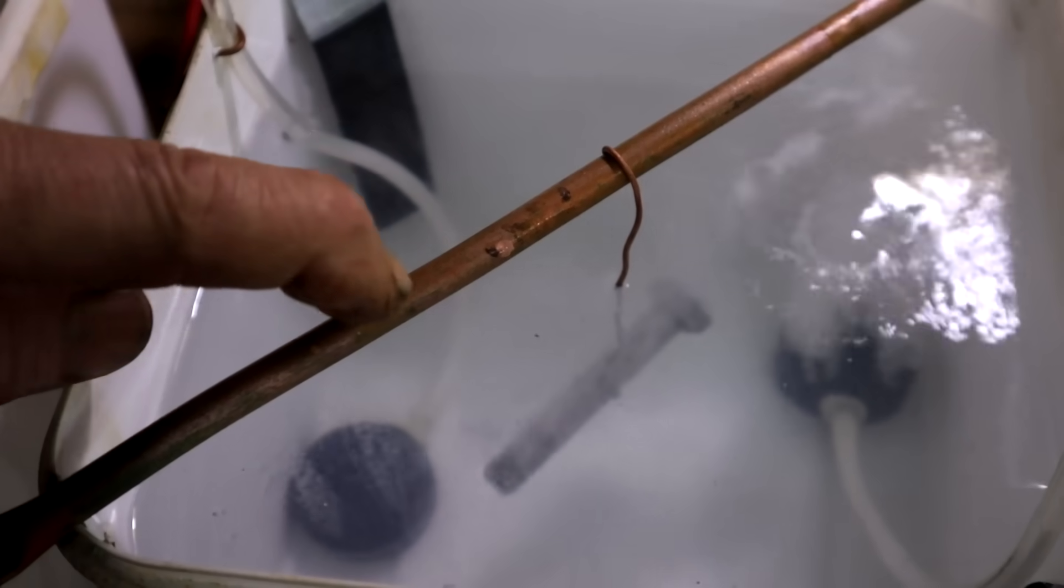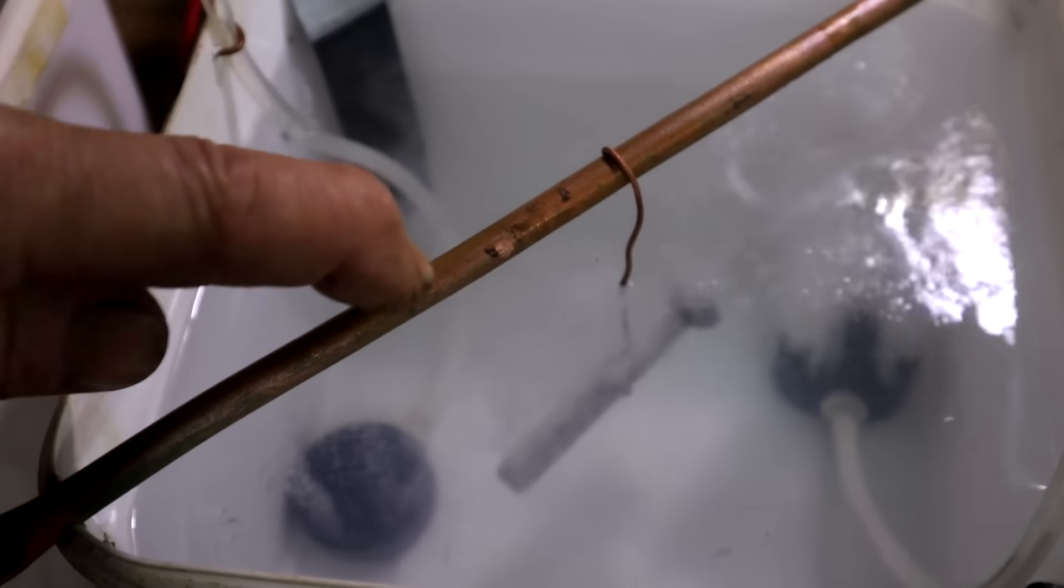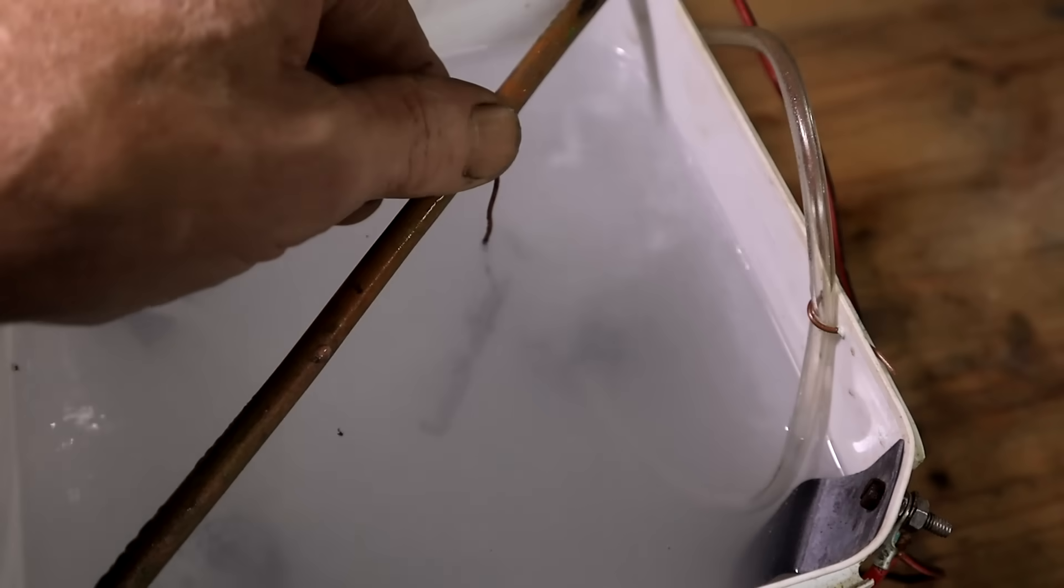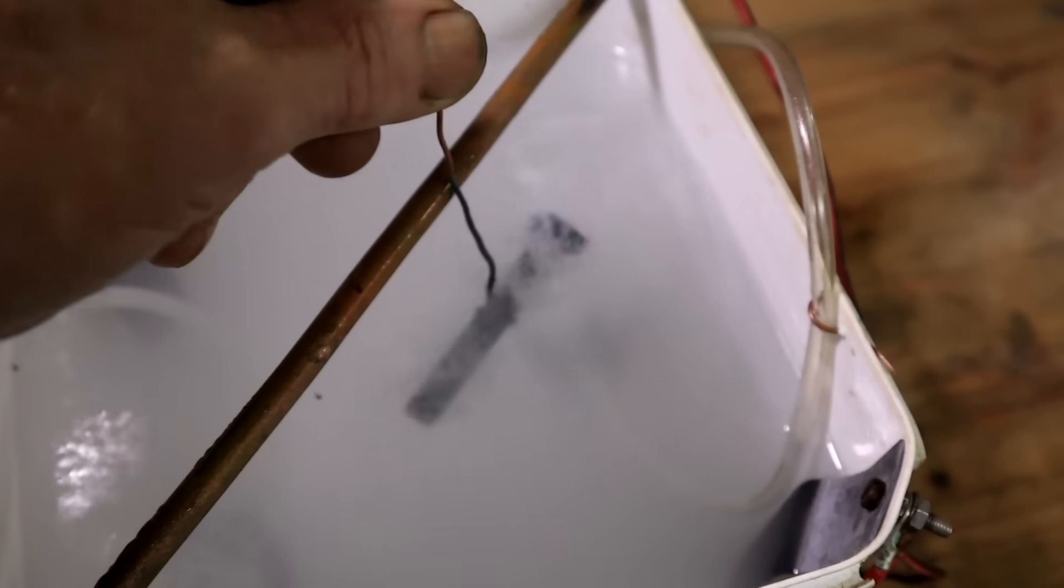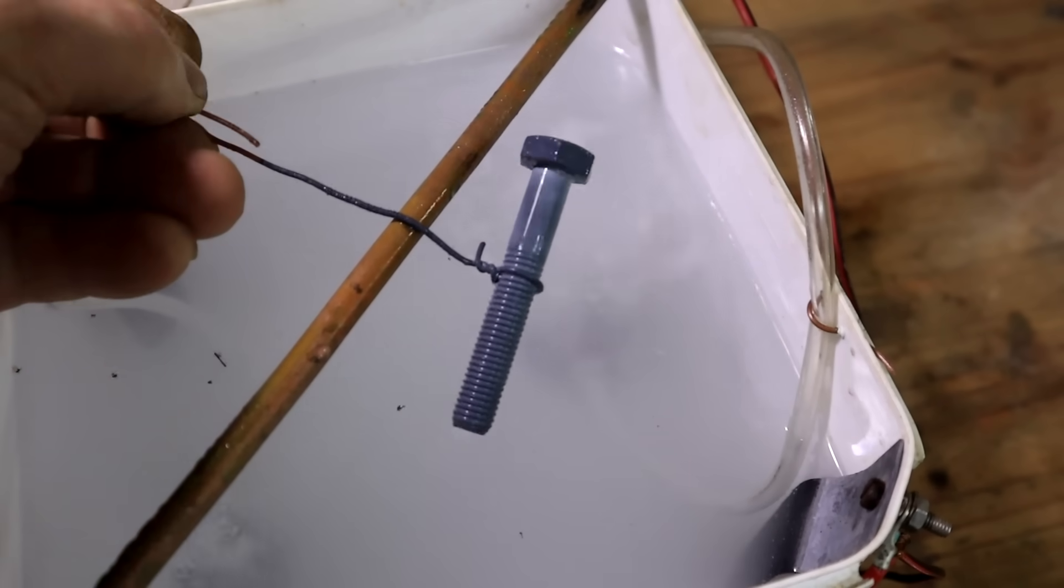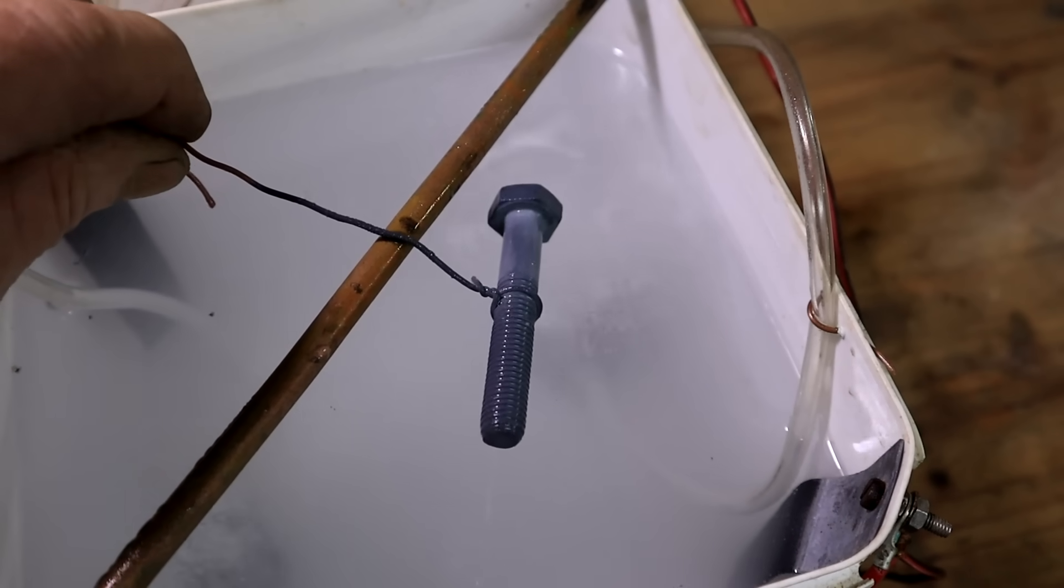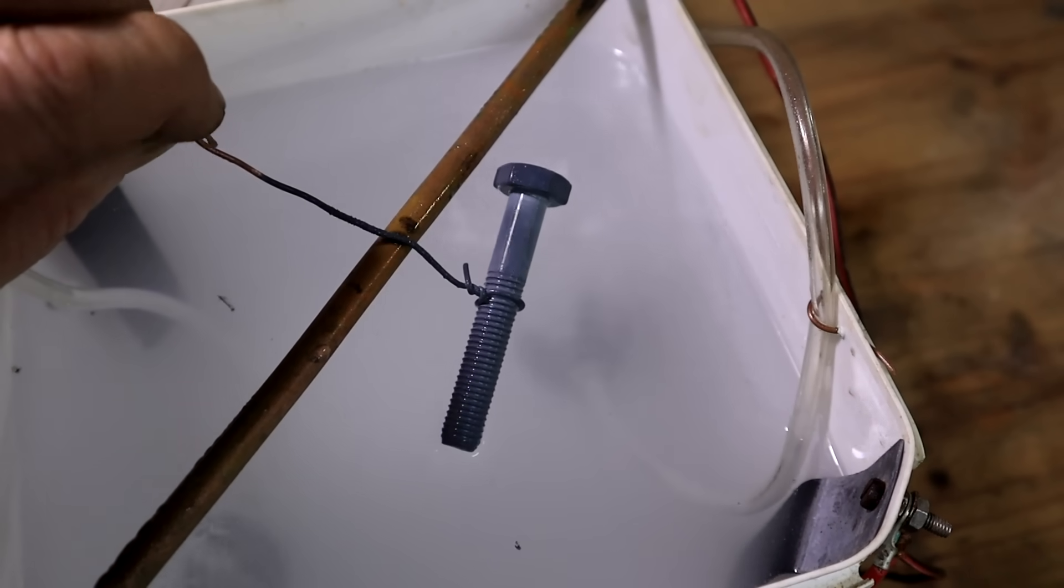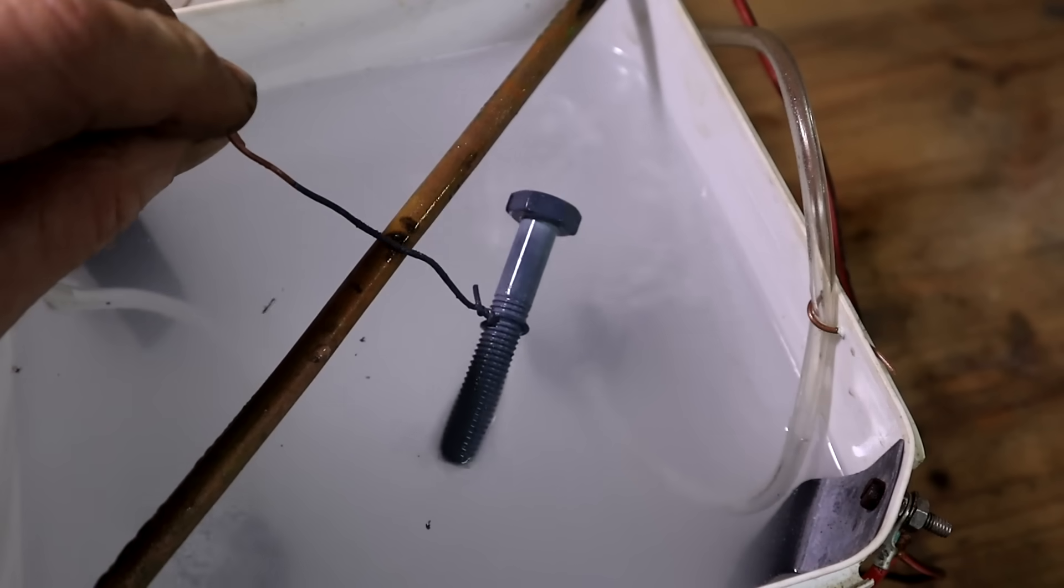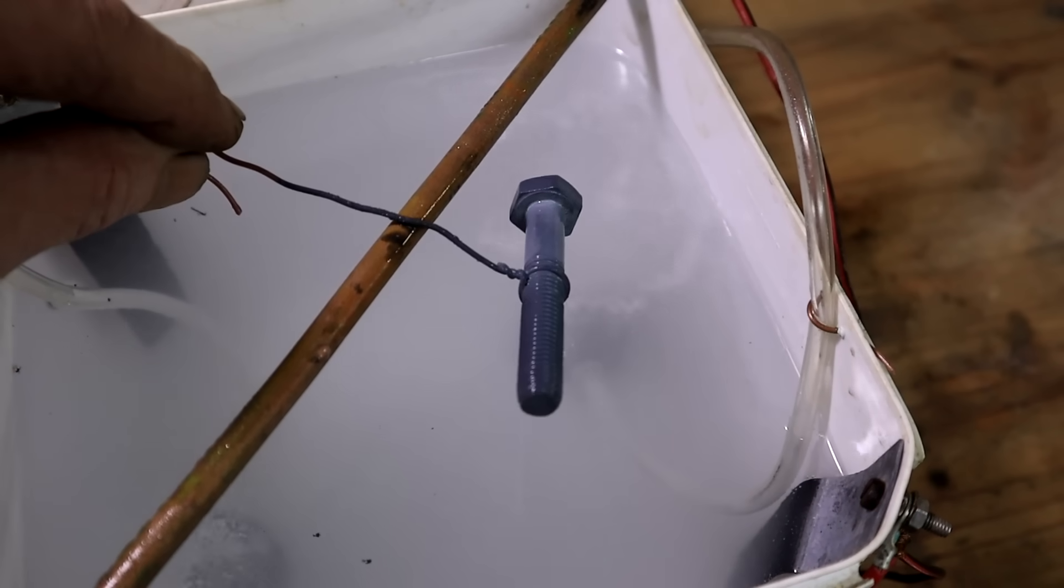I still got my power supply switched on. So this is connected to negative, that's important. Five minutes later, let's have another look. Ah yes, can you see? Now we've got a uniform gray color. So the bubbler has made all the difference. And that's why I've said earlier that it'll actually make for much better results. That looks good.